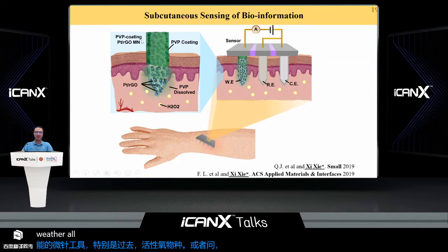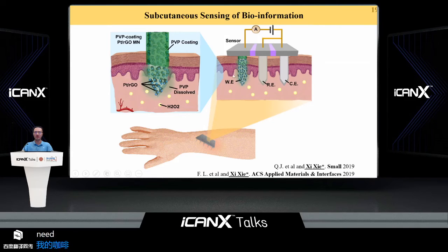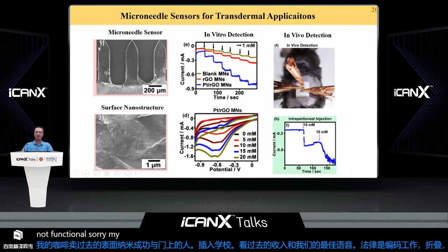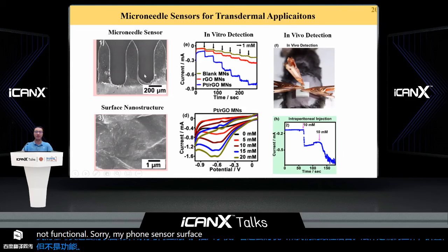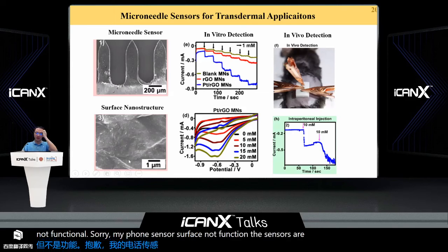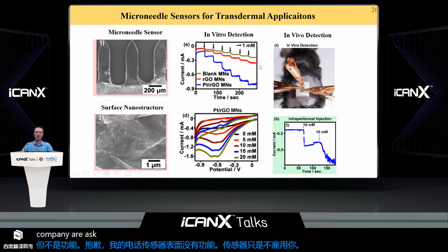So here we further develop a degradable polymer coating to protect the surface nanostructure when the microneedles are inserted into the skin. Once in contact with the interstitial fluid, the coating could be quickly dissolved, exposing the nanostructure to detect the biosignal. So here are the SEM images showing the morphology of the microneedle sensor and the surface nanostructure. This sensor shows very high sensitivity on detection of ROS underneath the skin of mice.